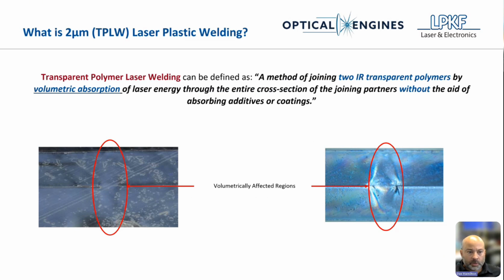All right, so transparent polymer laser welding can be defined as a method of joining two IR transparent polymers by volumetric absorption of laser energy through the entire cross-section of the joining partners without the aid of absorbing additives or coatings. We kind of coined this as the official definition for transparent polymer laser welding. And you can see from these images here, the one on the left, you can see the material interaction with the laser, and it's volumetric more or less from top to bottom. These are two pieces of plastic set on top of each other and welded in lap joint format. And you can also see another photograph of some welding, the laser interaction with the plastic.